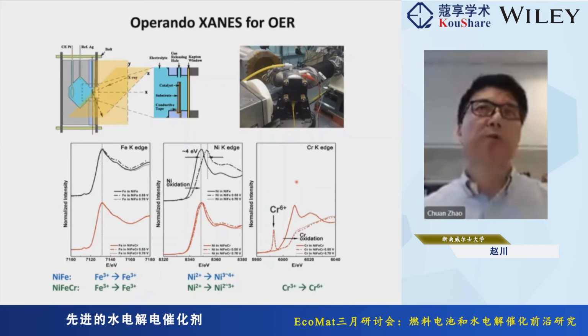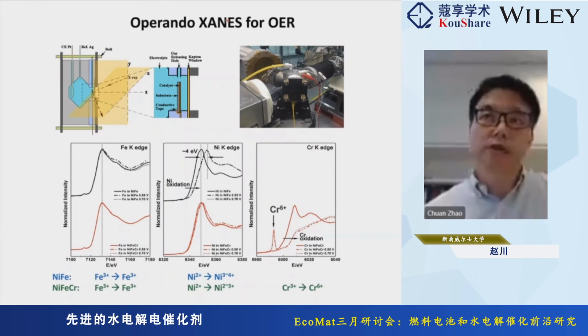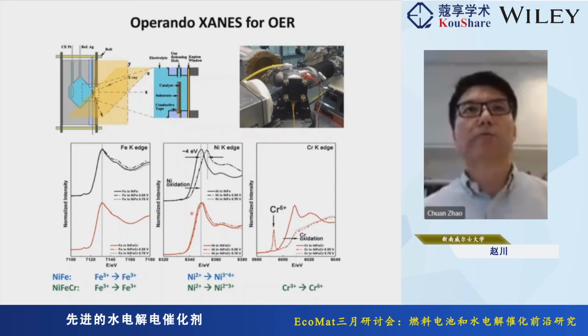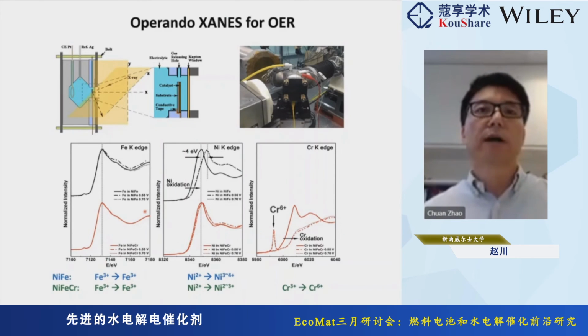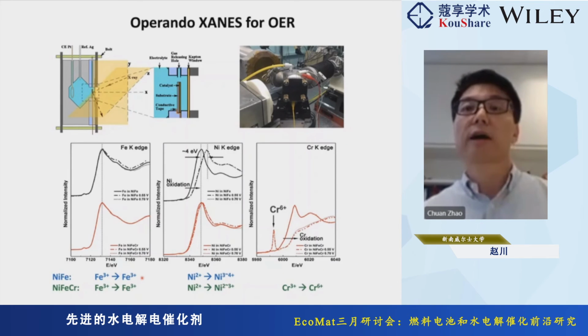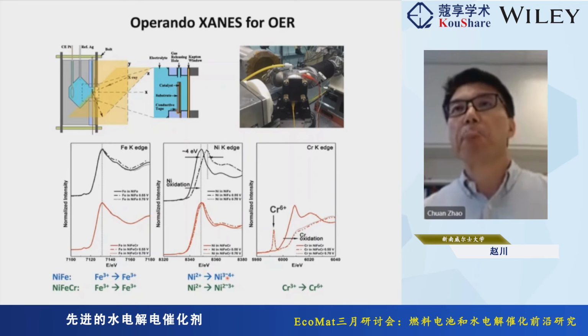And experimentally, with X-ray absorption near edge spectroscopy, we can find that the iron oxidation state remains unchanged in the nickel iron chromium, but there's a clear decrease in the nickel oxidation state compared to nickel iron.